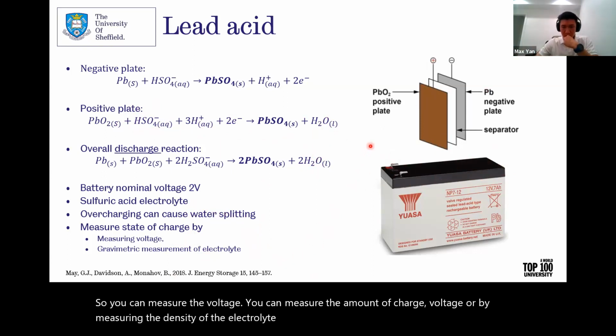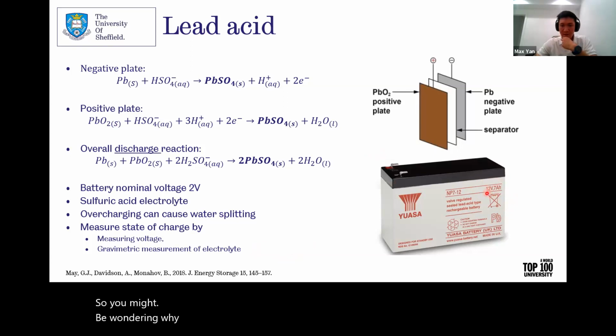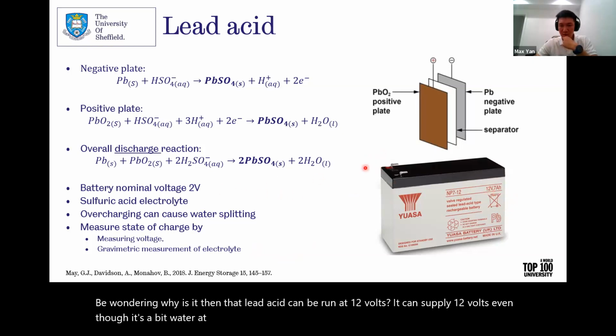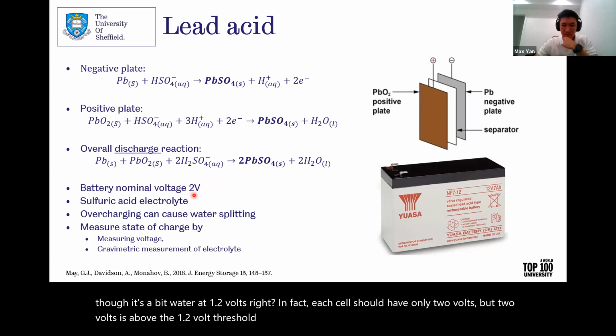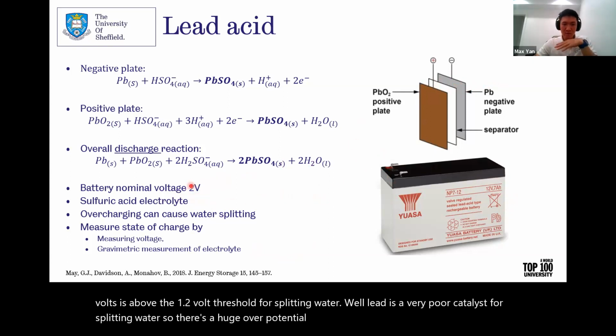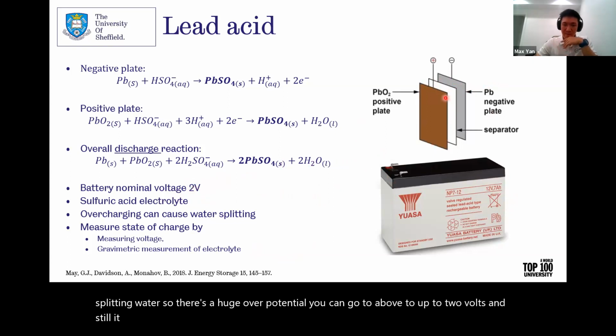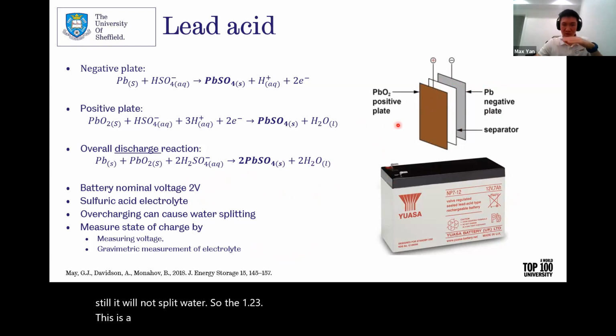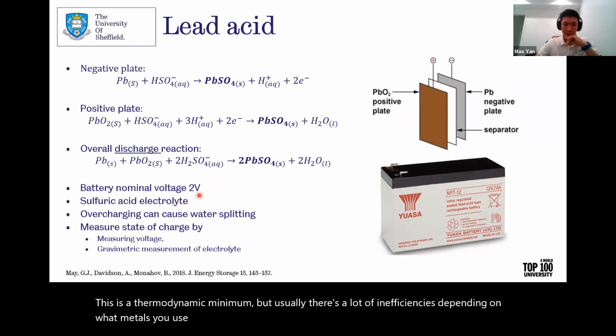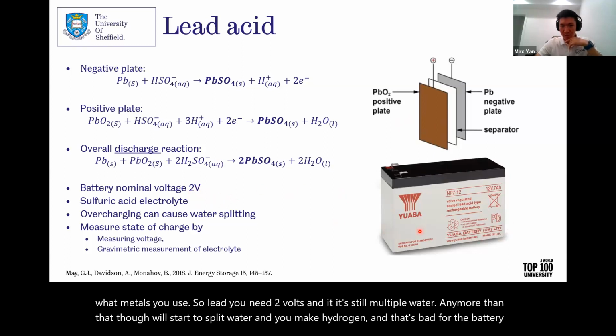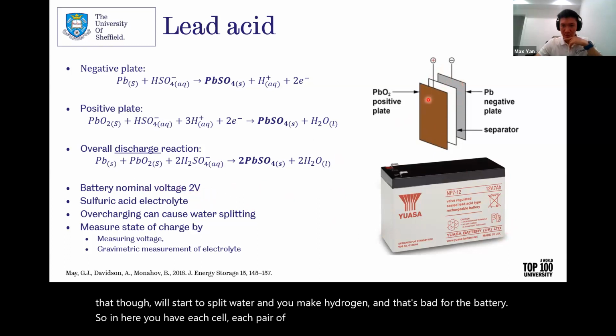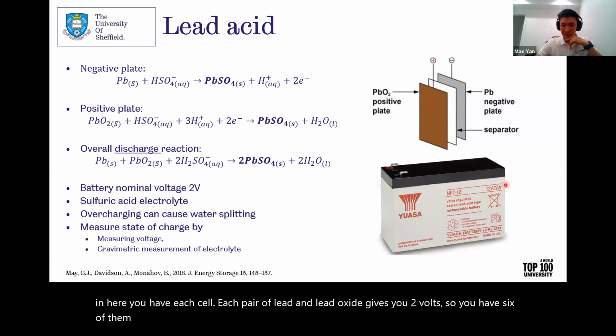So you can measure the amount of charge by voltage or by measuring the density of the electrolyte. So you might be wondering, why is it that lead acid can be run at 12 volts? It can supply 12 volts, even though water splits at 1.2 volts. In fact, each cell should have only 2 volts, but 2 volts is above the 1.2 volt threshold for splitting water. Well, lead is a very poor catalyst for splitting water. So there's a huge overpotential. You can go up to 2 volts and still it will not split water. So the 1.23 volts is a thermodynamic minimum, but usually there are a lot of inefficiencies depending on what metals you use. So with lead, you need 2 volts and it still won't split water. Any more than that, though, it will start to split water and you make hydrogen, and that's bad for the battery. So each pair of lead and lead oxide gives you 2 volts. You have 6 of them in series to give you this 12 volts.